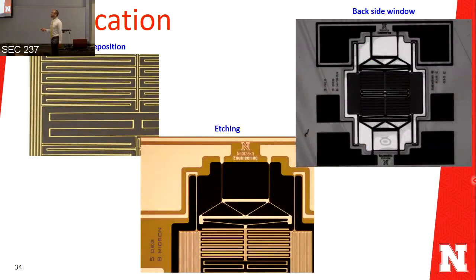So this is the device during the fabrication steps. Here I deposited the heater. Here I fabricated the front side of the device to realize the shape of the structures. And this shows the backside window via an IR camera. And this shows you how the backside etching is aligning perfectly behind the device.